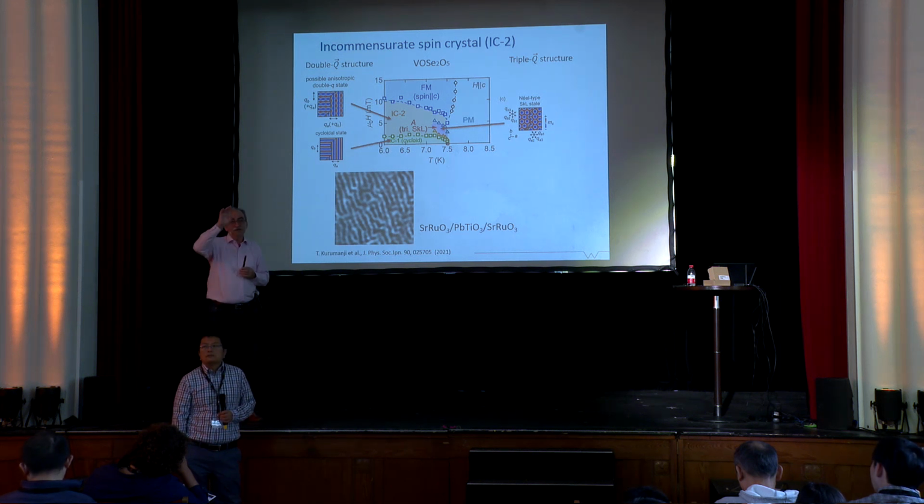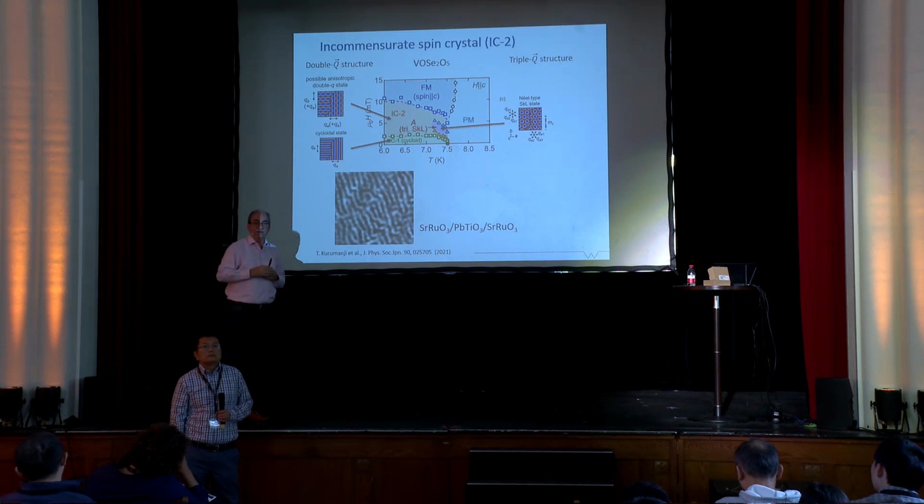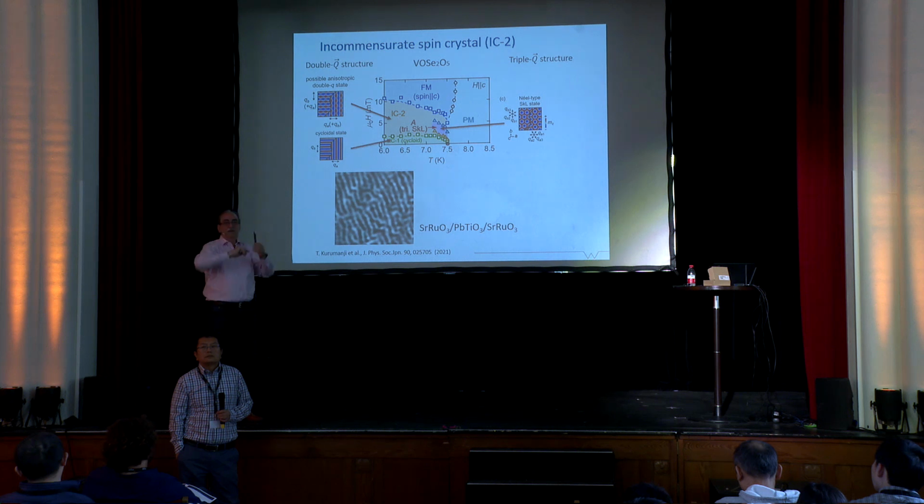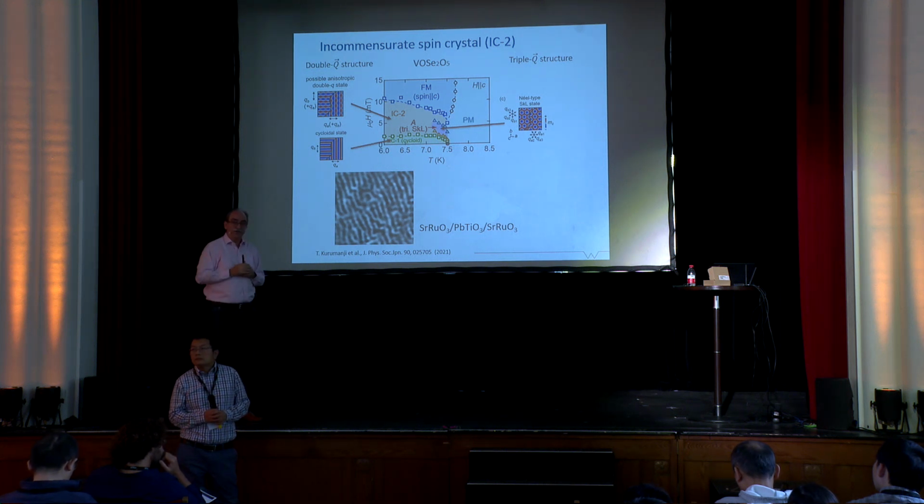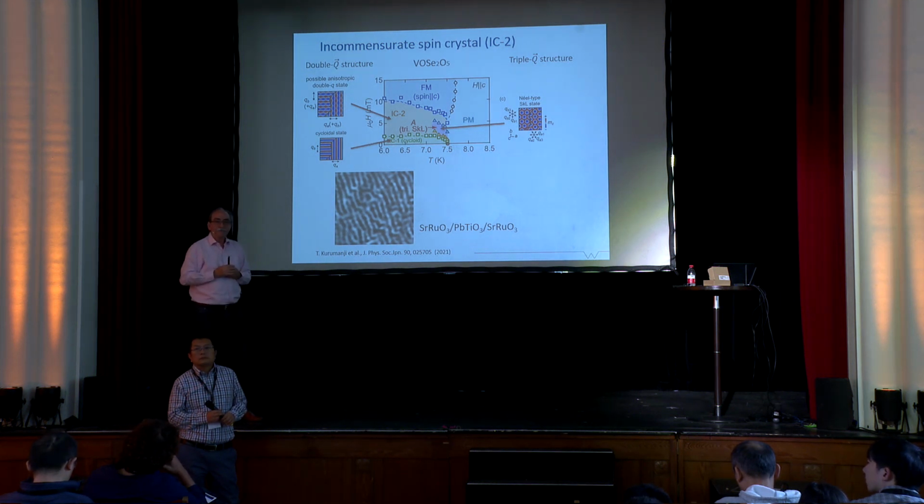If we speak of the lead titanate which has been used for strontium ruthenate, that is a bit thicker. It was something like 20 nanometers, and that goes into the normal ferroelectric phase without any problem, so all the dipoles are aligned upward. If you go into a thickness range of about 10 to 12 unit cells, you get that swirling phase. Otherwise, you won't get it. Thank you very much.